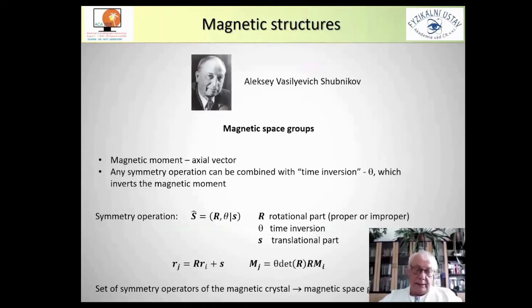And also, we had to take into account that any symmetry operation can be combined with time inversion, which inverts the magnetic moment. A symmetry operation, then, for a regular structure, is described by a rotation matrix, by a time inversion operator and a translation part. For position, it acts like this. This means x is changing by this equation. For the magnetic moment, we have, of course, no translation part, but we have here time inversion, and here the determinant of the rotation part, which means it's taking into account that the magnetic moment is an axial vector. The set of symmetry operations of a magnetic crystal makes a magnetic space group.